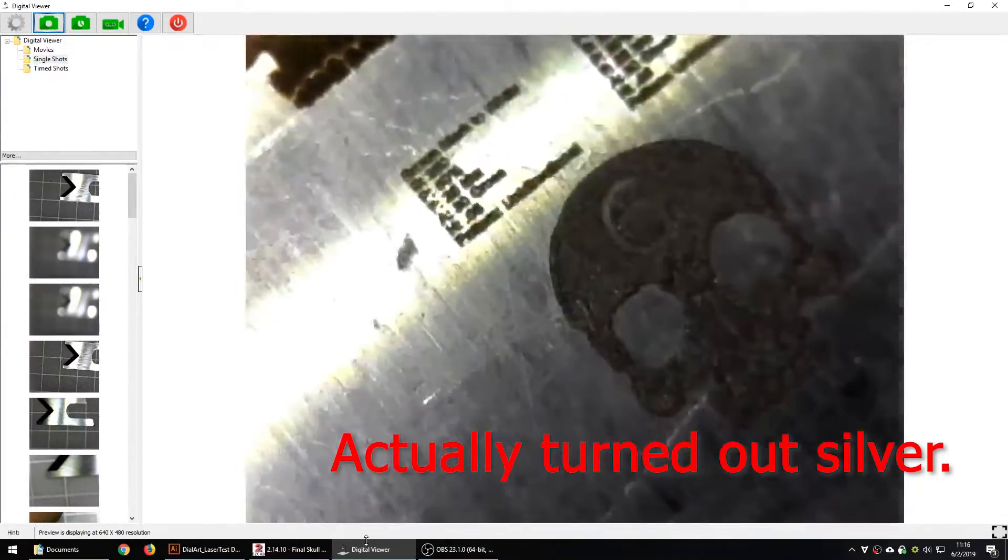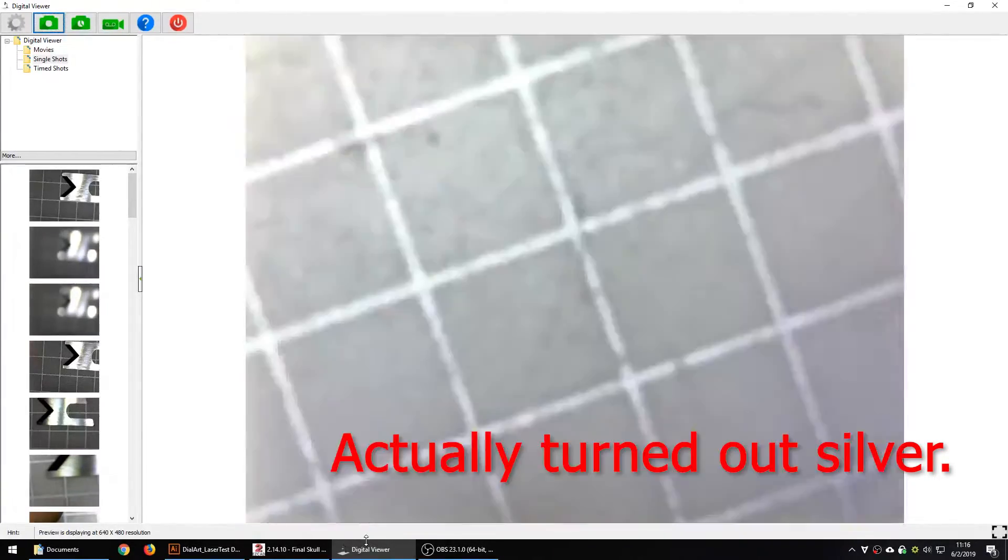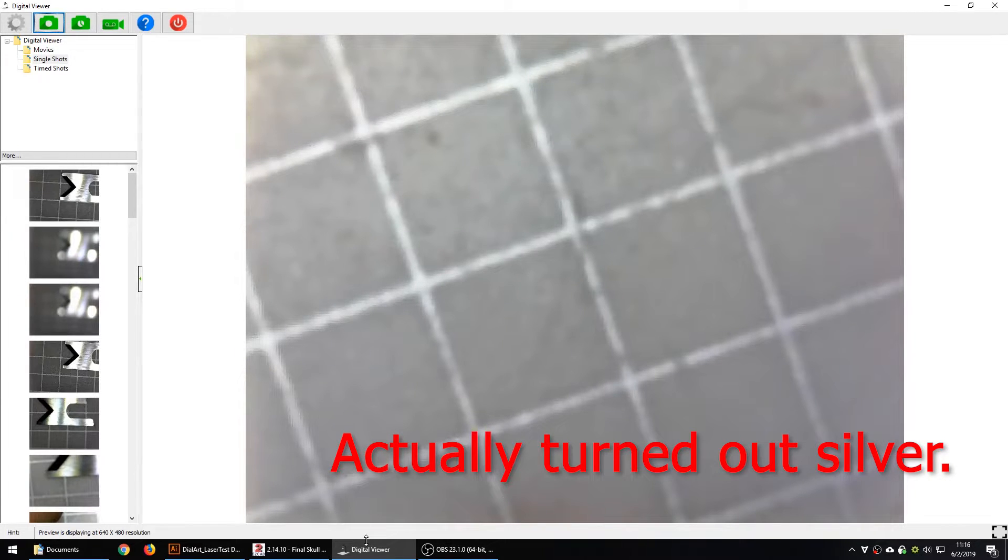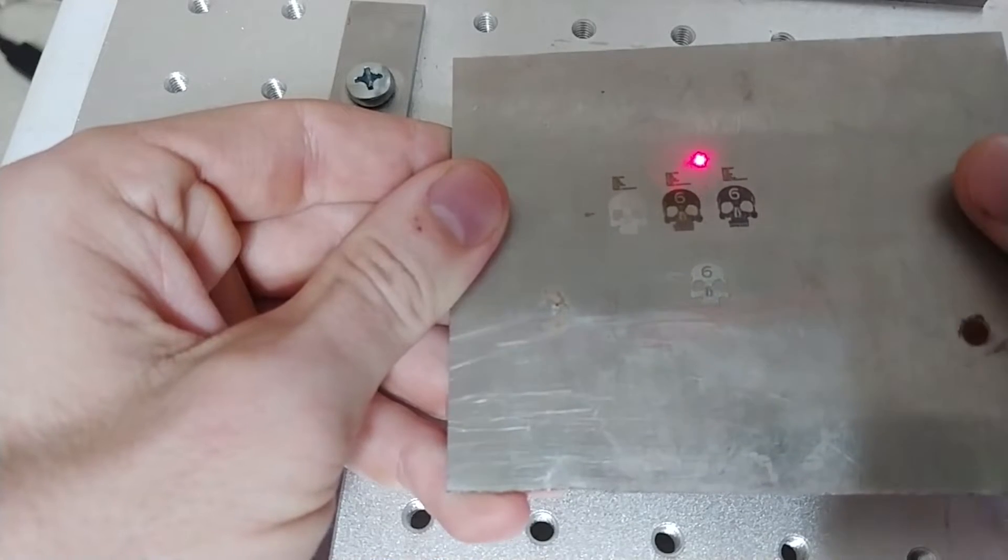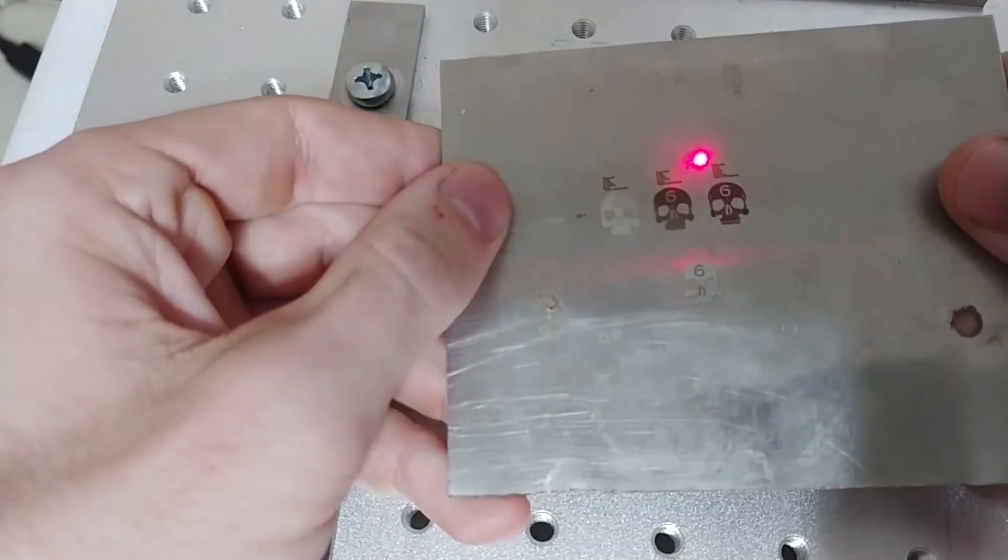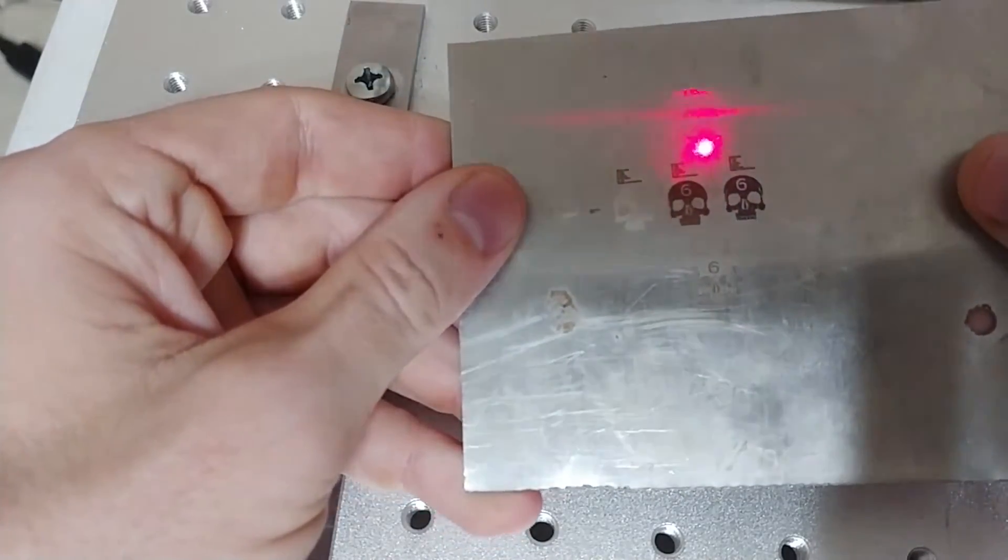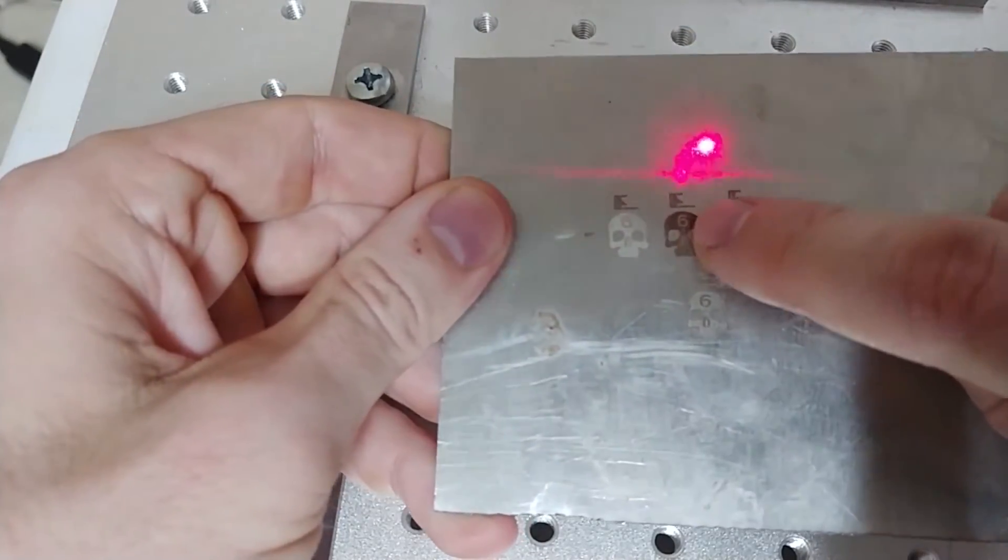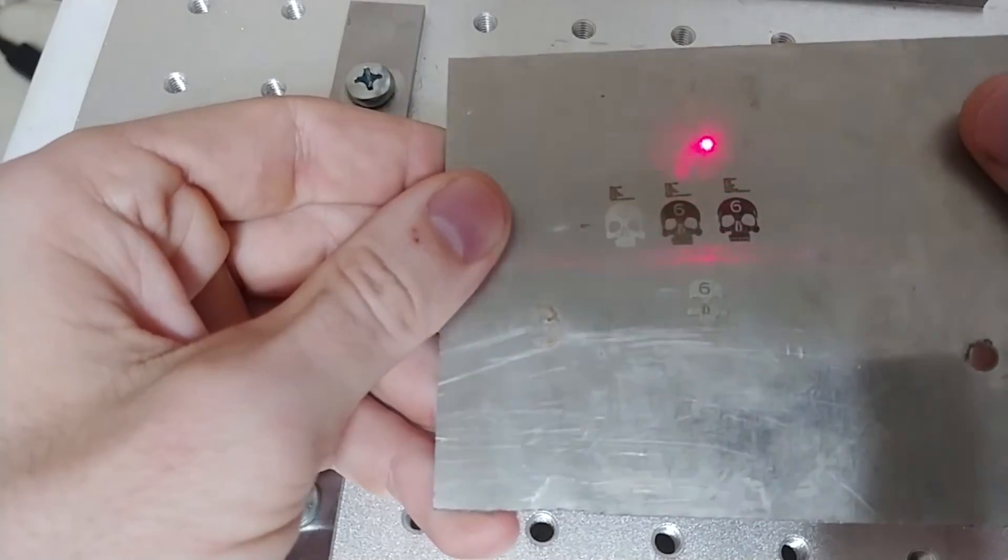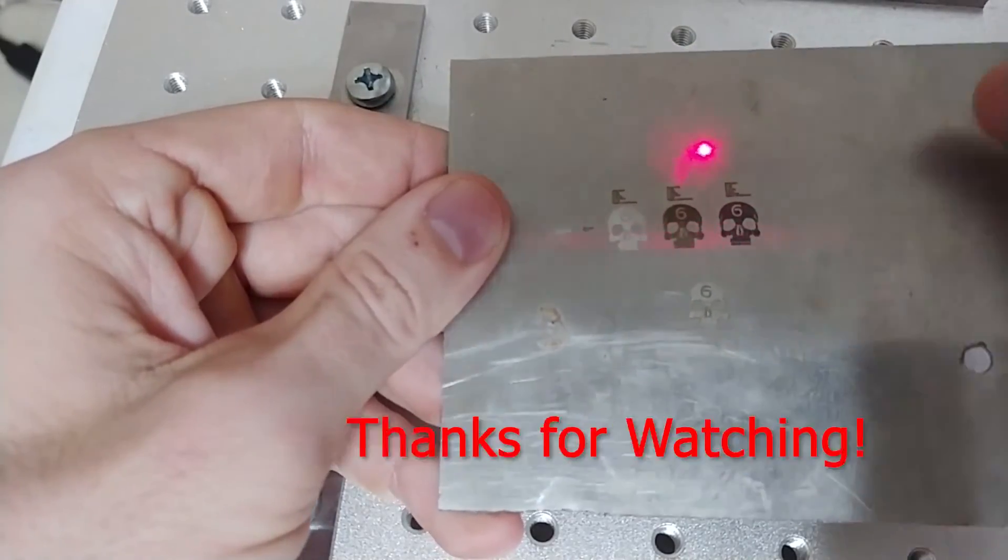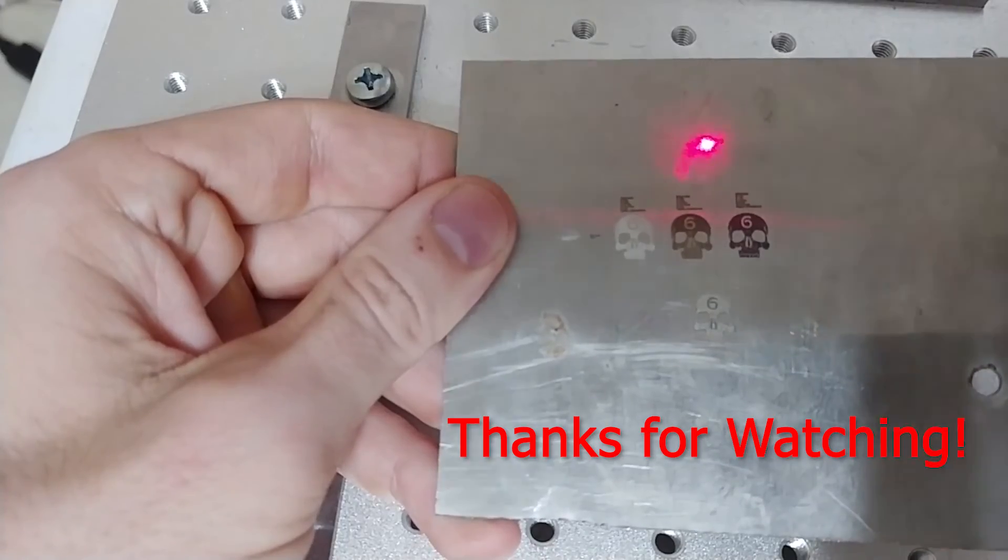The mark is not quite as white as the first mark. It's a little bit silverish. You can sort of see, here's the white mark. This is the repeat with the brown and then the white mark. Slightly silverish, but significantly lighter than that brown mark. So I guess you can run a cleanup pass and make your mark white after it's brown.